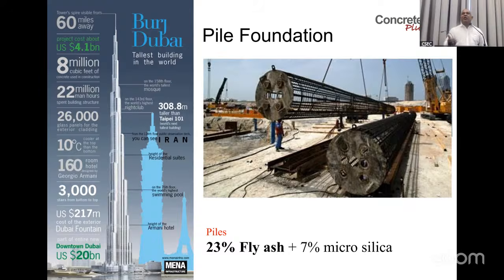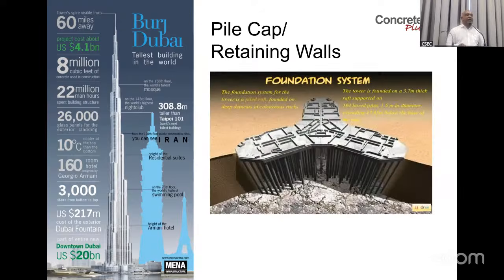So our question is, why 23%? Why microsilica only 7%? Because just to have durability, if you use fly ash, you need at least 25% fly ash alone. But when you use a combination with microsilica, around 25% or above will give you very high durability plus strength. That's why they have gone with microsilica, to get the required strength, workability and durability with the combination of these. So that's why they have gone 23%, not 10%. Now this is done.